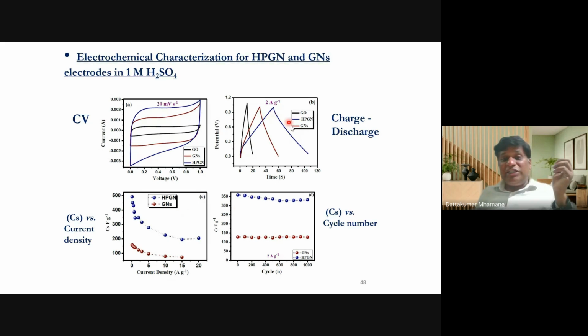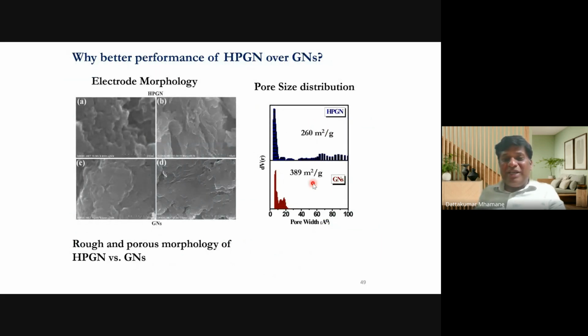You can see the discharge time for perforated graphene is very high, but that of graphene without perforation is very less. Again, the charge storage performance, the supercapacitor performance at 2 ampere per gram. Perforated graphene performs well. However, the non-perforated is only 130 or 140 farad per gram. So these are the, I told you, it's not possible to increase the surface area of graphene. See, our perforated graphene has a surface area of only around 260 square meters per gram, and that of chemically prepared graphene is around 400. Still perforated graphene is performing well because the number of edge sites, number of holes are more. So catalytic sites are more. So electrolyte interactions are very high with perforated graphene when compared with graphene which does not have any kind of holes or perforations. Okay, so you can see the porous morphology of perforated graphene, whereas it is rough morphology in the case of graphene without perforation.